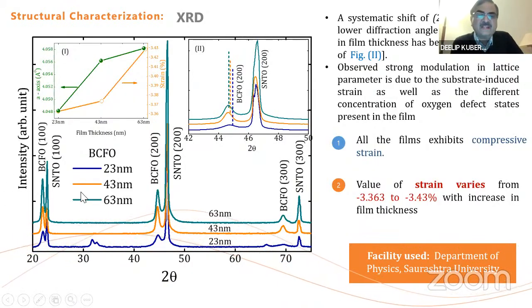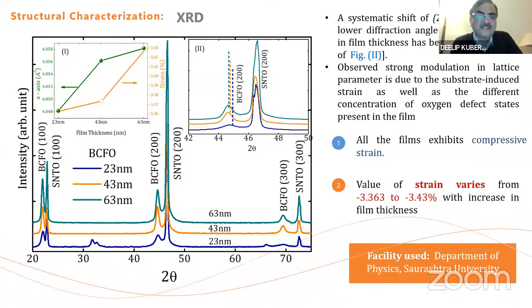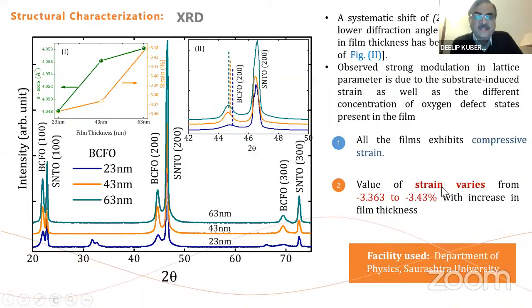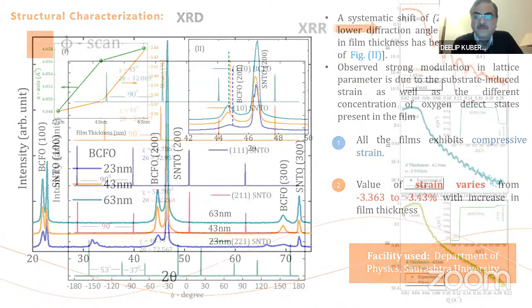So here is the X-ray diffraction pattern, and here you can find out the strain using the formula, which is a very popular formula for doing the strain, whether it is a tensile strain or a compressive strain. So I saw that the strain varies from -3.363 to -3.43% with increase in the film thickness. So as the film thickness increases, the strain value always changes. So you can see here the strain is dependent on the film thickness, which is very well studied.